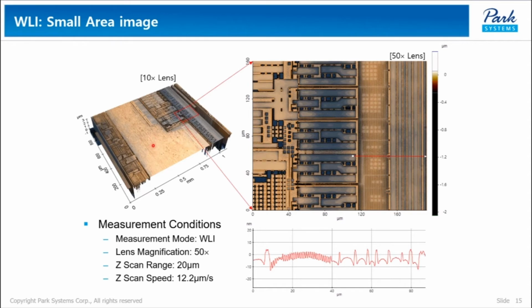Changing the lens in WLI from 10x to 50x using a motorized turret gives us higher resolution images quickly. In this region of interest, we changed the lens to 50x using the motorized turret. In this result, a 10 nanometer step height sample with a feature size around 1 micrometer was successfully measured. In conclusion, metrology capability was proved by the aforementioned result. The remaining work is application function testing like auto stitching and defect reviewing, and these are being tested right now.